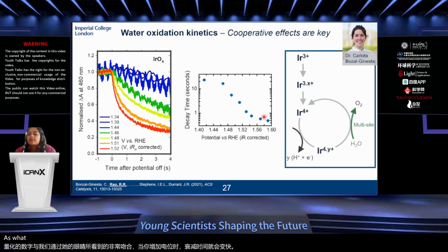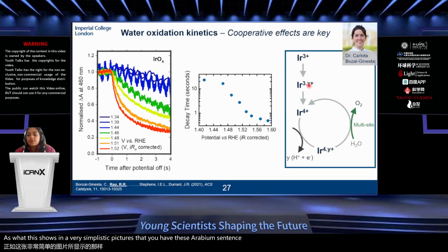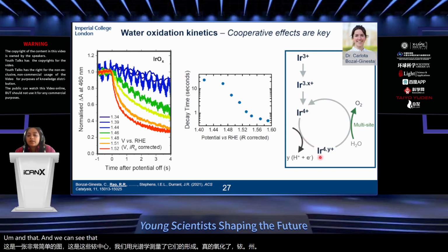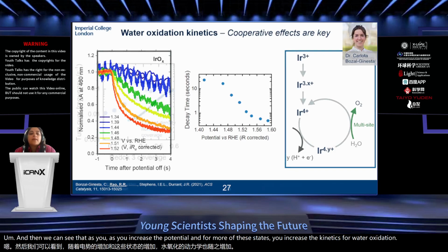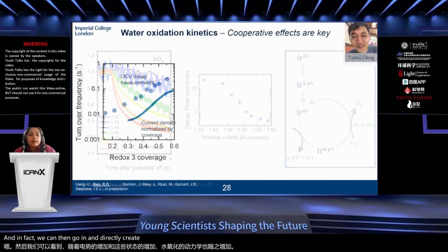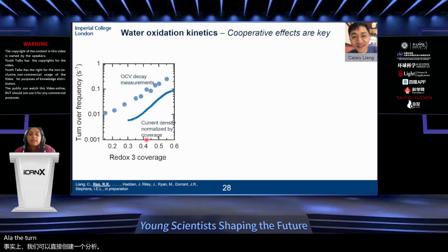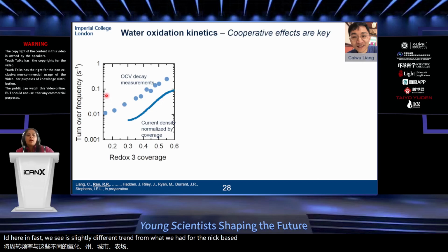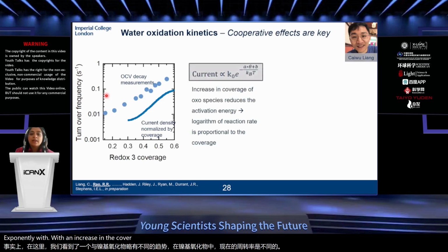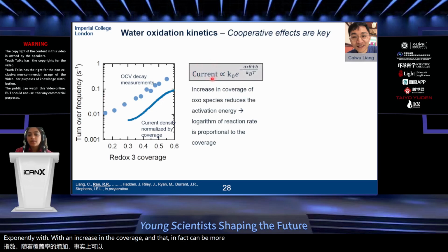So what this shows in a very simplistic picture is that you have these iridium centers. We've measured with optical spectroscopy the formation of these really oxidized iridium states. And then we can see that as you increase the potential and form more of these states, you increase the kinetics for water oxidation. And we can then go in and directly create an analysis where we relate the turnover frequency as a function of the coverage of these different oxidized states that you form. And here, we see a slightly different trend from what we had for the nickel-based oxides, where now the turnover frequency scales exponentially with an increase in the coverage. And that can be modeled using this equation here, where the current scales exponentially with the coverage.